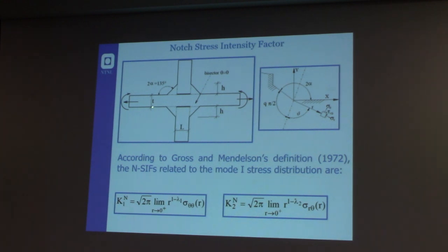The problem is that, as we have discussed before, we have different units of measure here and here. So usually the notch stress intensity factor is very powerful if you have failure only from the weld toe. Usually, if the weldment is well designed, we don't want internal failure. So actually, we always want to detect the initiation of cracks from the outside. We don't want the crack to start from the inside. So if we make a good design of the weldments, the majority of the failures happen from this point and not from this point.